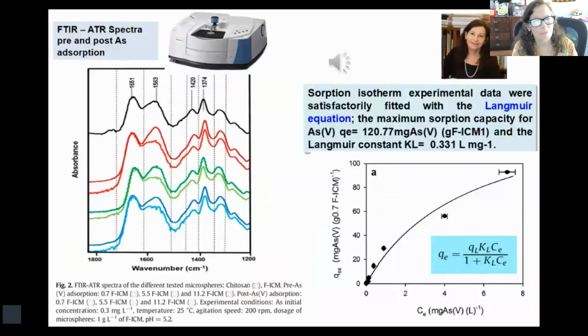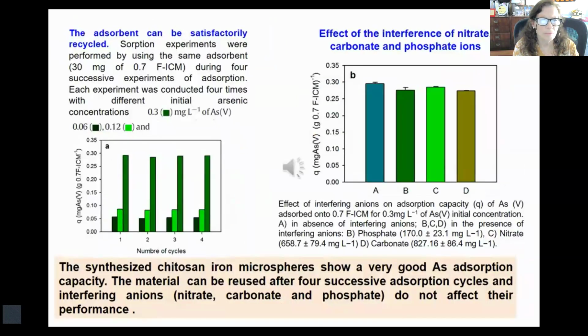We analyzed the FTIR spectra of the tested microsphere pre- and post-arsenic adsorption. Sorption isotherm experimental data were satisfactorily fitted with the Langmuir equation. The synthesized chitosan iron microspheres show a very good arsenic adsorption capacity. The material can be reused after 4 successive adsorption cycles, and interfering anions such as nitrate, carbonate, and phosphate do